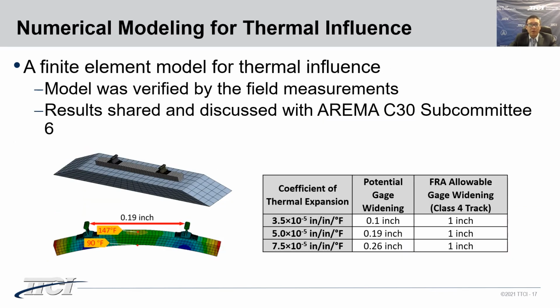A finite element model was built to further investigate the thermal effect on composite ties. In order to verify the model, the previous in-track temperature and gauge widening measurements were used. The temperatures at the top and bottom surfaces of the tie in the model were set to be 147 degrees and 90 degrees respectively, same as the in-track measurements. Modeling shows a 0.19 inch widening, which was close to the in-track detected value of 0.2 inch.